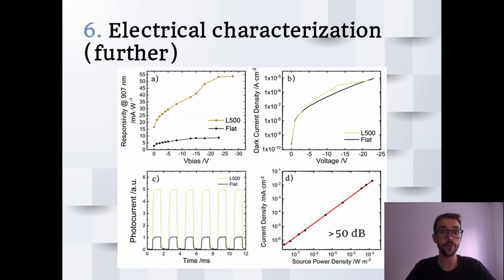We performed some further characterization on the photodetectors to evaluate their performance when comparing them to flat non-structured photodetectors. In the case of the responsivity, we can not only see that it's much higher for the nanostructured photodetectors than for the flat ones, but that the saturation voltage at which all the charges have been extracted occurs at much lower voltages.